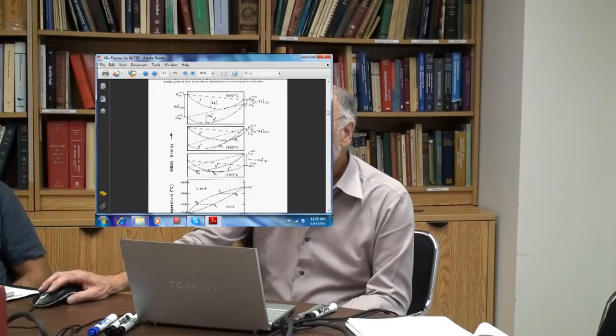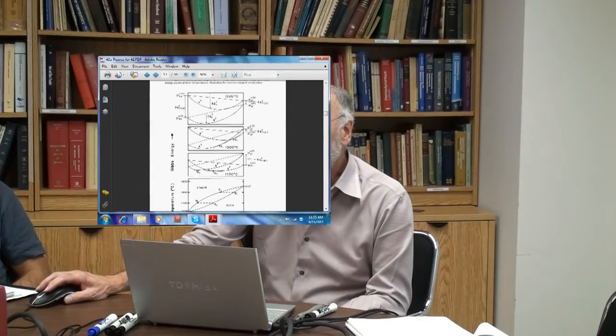Okay, the G of the solid phase goes from the chemical potential of pure germanium in the solid, mu naught germanium solid, over to the chemical potential of mu naught silicon in the solid, and the liquid phase goes like this. This distance here is mu naught silicon liquid minus mu naught silicon solid, in other words, the Gibbs energy of fusion of silicon. And this distance here is the Gibbs energy of fusion of germanium. This is the Gibbs energy of mixing of the solid phase, and this is the Gibbs energy of mixing of the liquid phase. Everybody cool with that one?